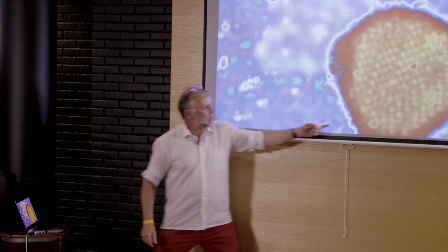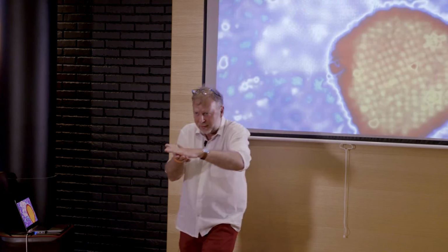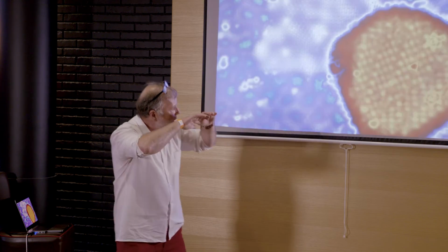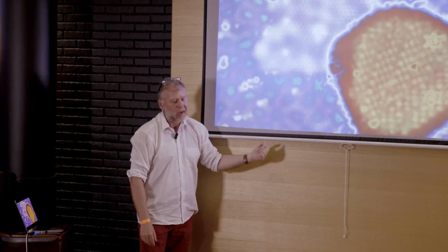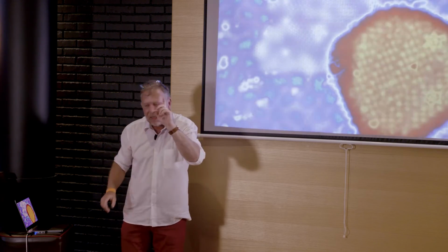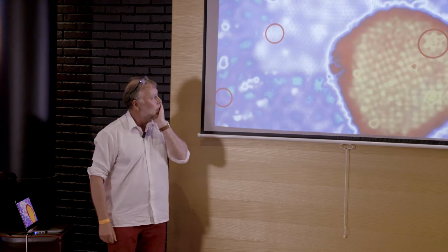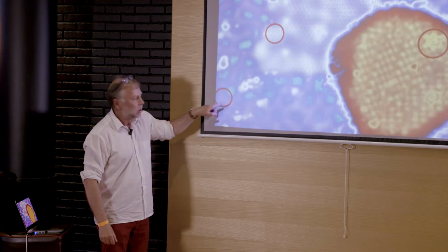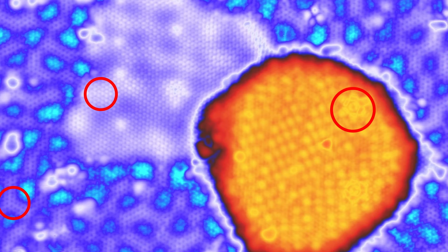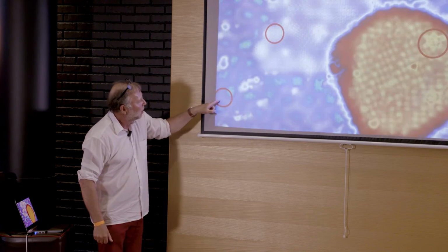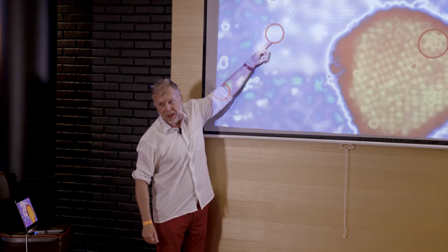But nevertheless, this is a cobalt, flat cobalt. On it there is this graphene, and below all that there is the silicon carbide that you don't see there. Maybe we can see it by transparency. This is the famous, you see there something here with hexagonal shape, the honeycomb is here. So each point here corresponds to a localization of many electrons around the carbon atom. Sometimes it is bilayer like that. We can understand that.